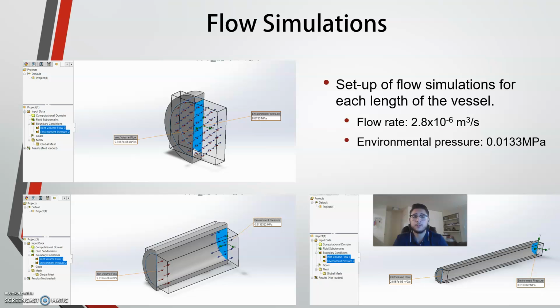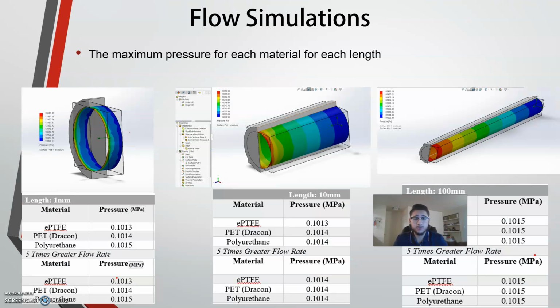For the second run of the simulations, a worst-case scenario test was conducted in order to analyze the response of the vessel in a flow rate that is 5 times larger than the common blood flow. This flow rate was determined to be 1.4 times 10 to the negative 5 meter cubed per second. The environmental pressure inside a human body was inputted as 0.0133 megapascals, as you can see in the SolidWorks screenshots. The maximum pressure for each material and for each length was recorded.